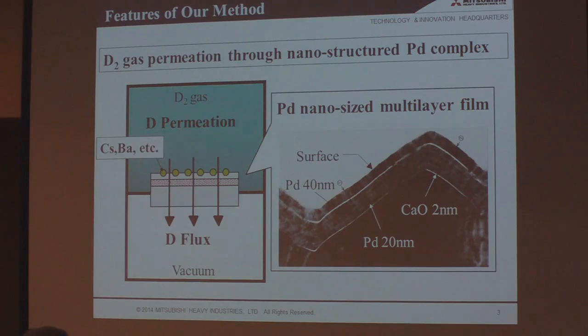Introduction. Our experimental method is characterized by the D2 gas permeation through nanostructured palladium complex. This is a cross-sectional view of the palladium nanostructured multilayer thin film. The white region corresponds to the calcium oxide, and black corresponds to the palladium. Using this multilayer thin film, we put the elements in advance on this side, before permeation. For example, cesium or barium, we put on this surface by ion implantation or other methods.